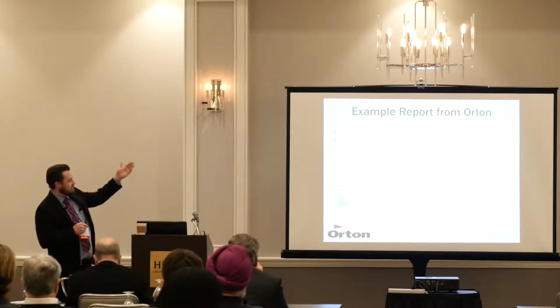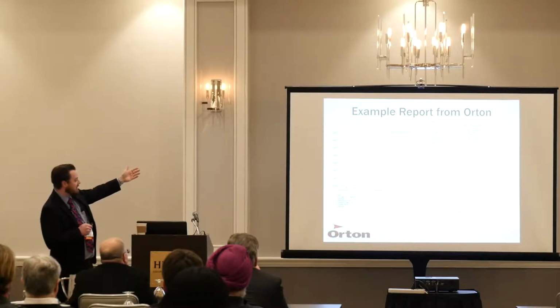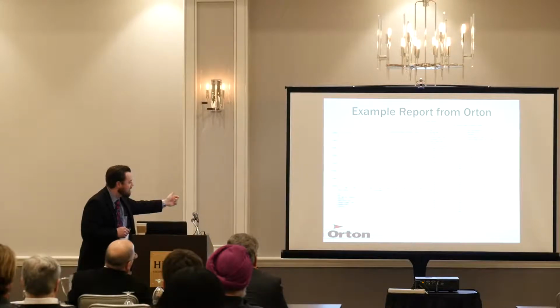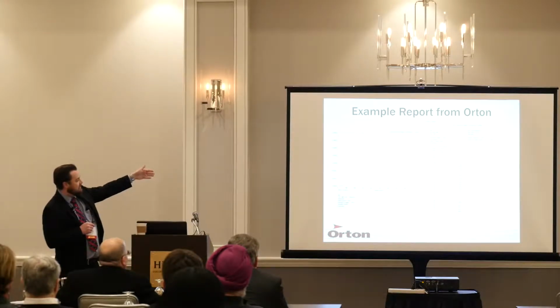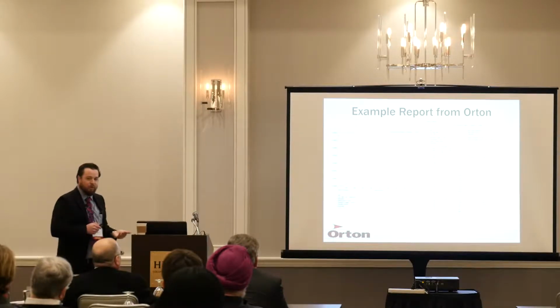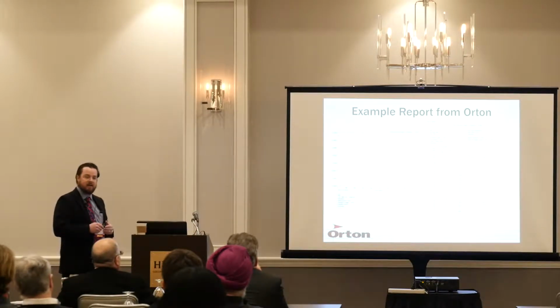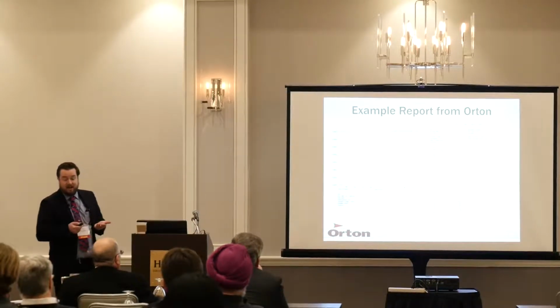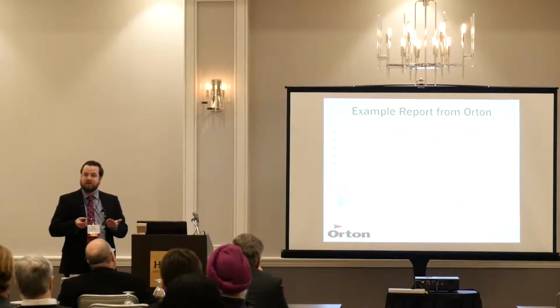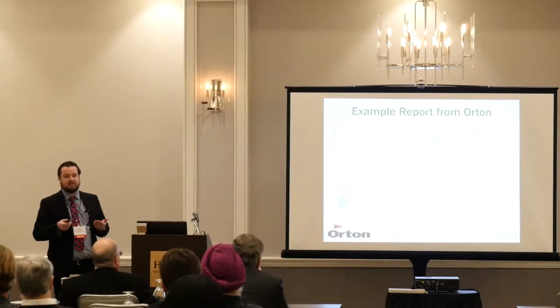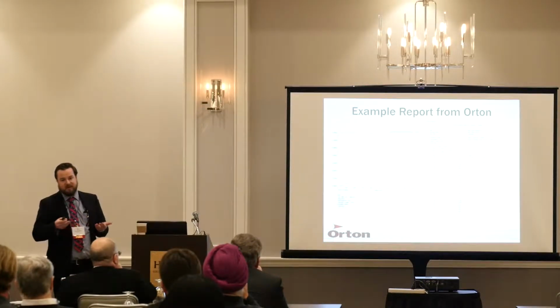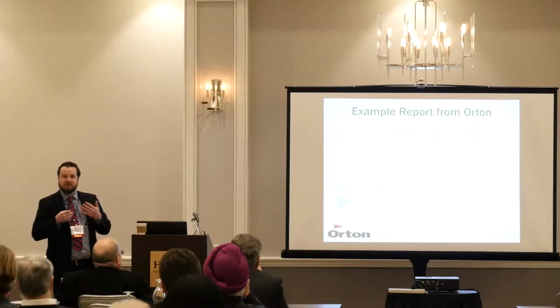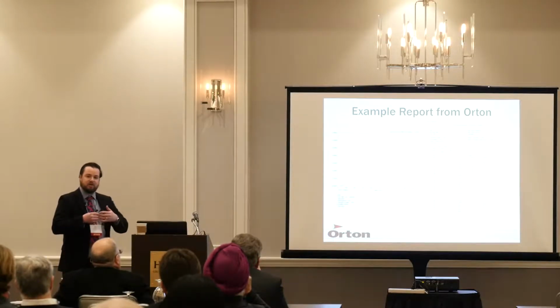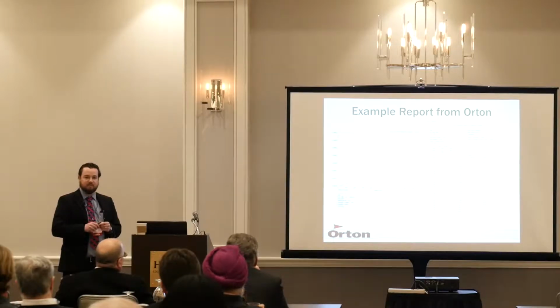But here on the left is similar to the calibration runs. This might even be a metal itself. But you can see that you're going to have a percent linear change on the left side in the temperature range. So you can start to understand where your material is going to perform. I'll show you some examples of different materials. You can start to qualify, hey, is my material what I think it is? Is it going through any transformations? Is it expanding too fast? Is it cooling too fast? You might have a mismatch with my body glaze fit. So it's just a tool to help you understand your material performance and response.